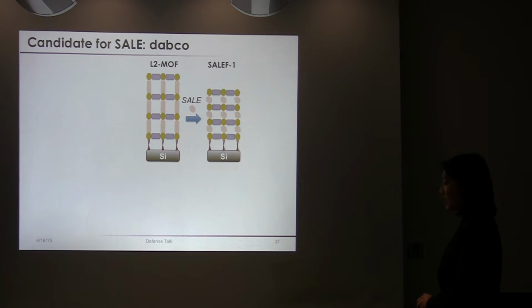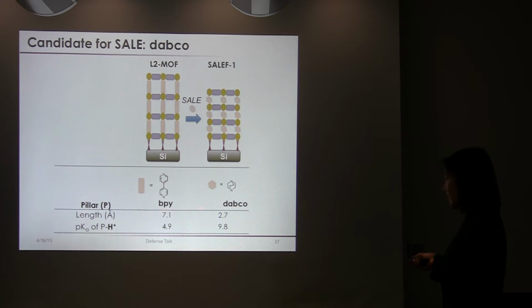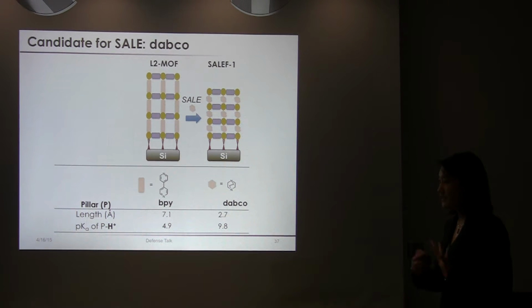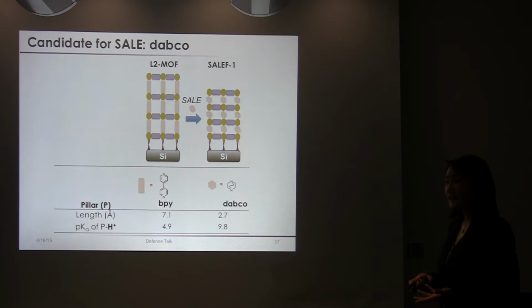So as a candidate linker for exchange and replacement of the bipyridine linker, I chose this 1,4-diazabicyclooctane, DABCO, pillaring component, mostly for two reasons. One of them being that there's a difference in length between the bipyridine and the DABCO unit by more than 4 angstroms. And secondly, there's a difference in pKa of the conjugate acid. In our previous works, we have noted that if the pKa of the conjugate acid of the replacing linker varies from that of the pillar being replaced by more than 2 pK units, then SALE essentially goes to completion. So by picking DABCO as a candidate for SALE, I hypothesized that SALE should also go to completion in a thin film form.